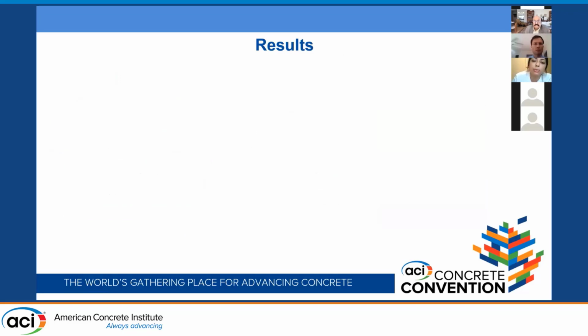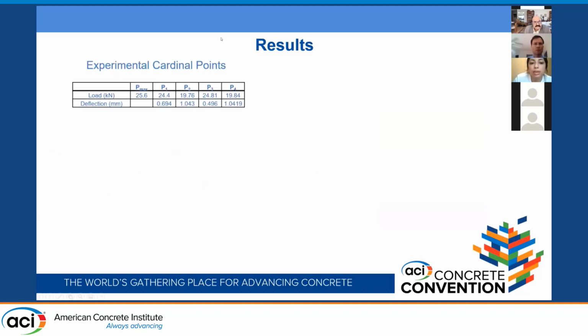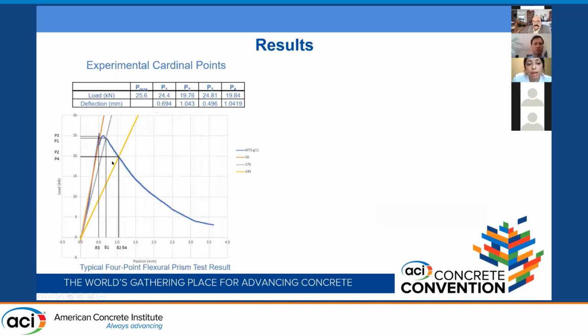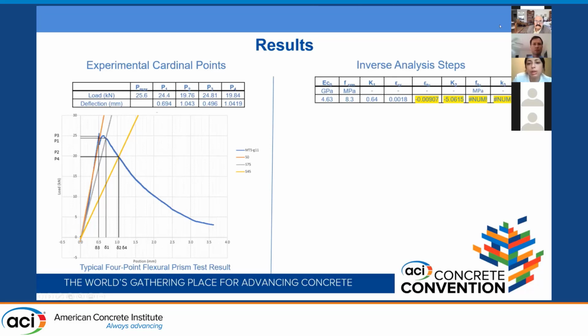As I mentioned previously, the code implies that P3 has to be greater than P2, and this is satisfied in here. However, when we look at the graph, we can tell that this is S0, this is P1, which is the 75% of the initial stiffness, and this is P2, which is the 40% of the initial stiffness. You can see that P1 and P2 are in the softening region. They're not even in the hardening region, and P3 is actually greater than P2, so the code limit is satisfied. However, the method yields, when we are doing the inverse analysis, unrealistic numbers.